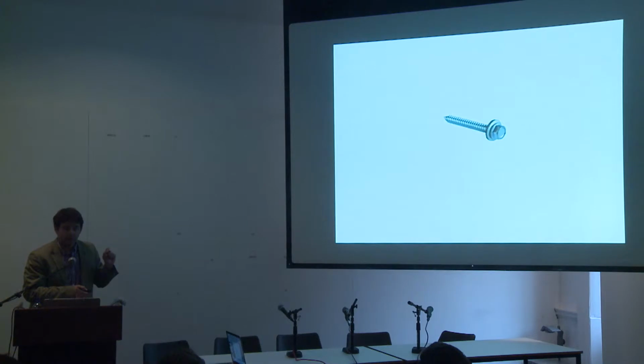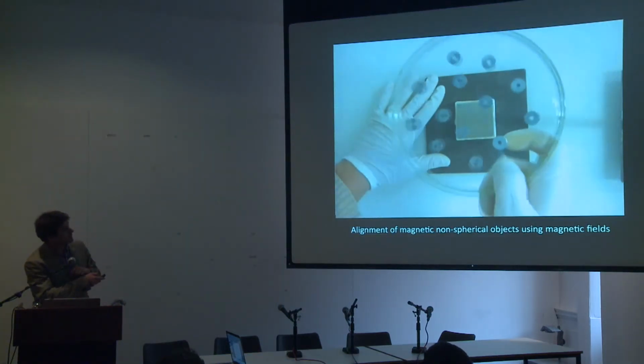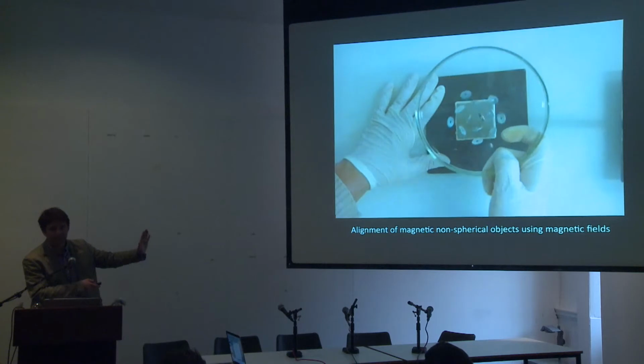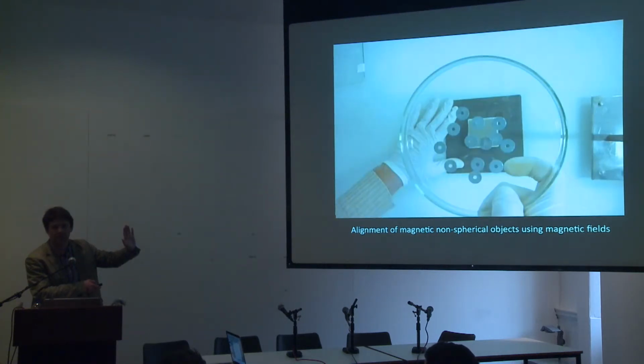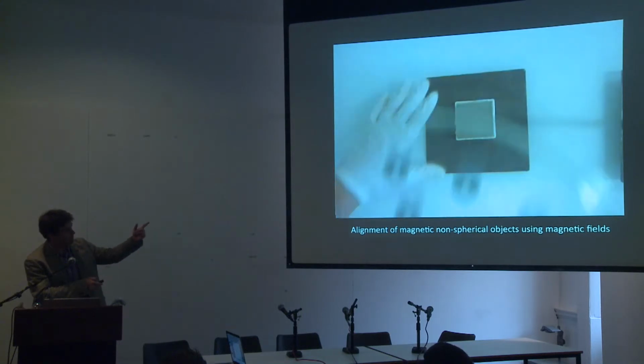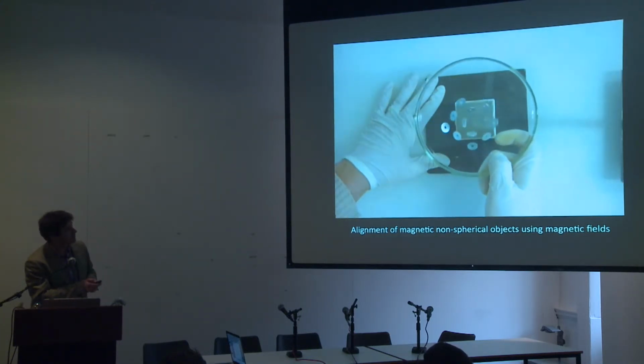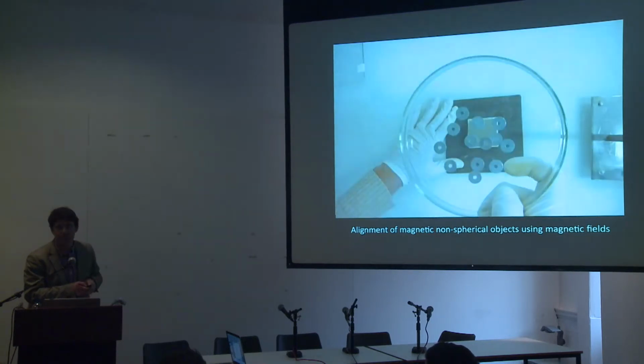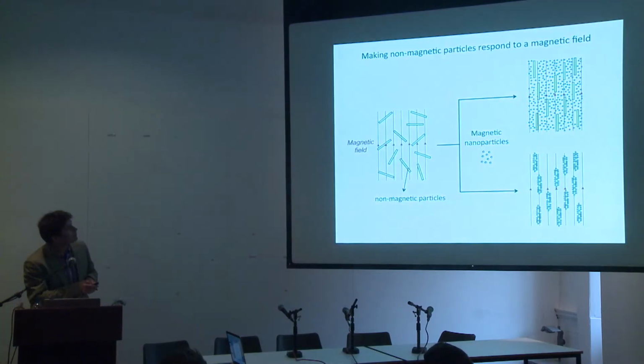So the technology we use to align these anisotropic particles is very simple. It's based on the application of an external magnetic field. And I usually illustrate this concept using this macroscopic example. If you take metallic washers and you put them on top of a magnet, you will see something like this. They will all orient parallel to the direction of the applied magnetic field, which in this case is coming out of the screen. So it is this very simple concept that we use in this technology.